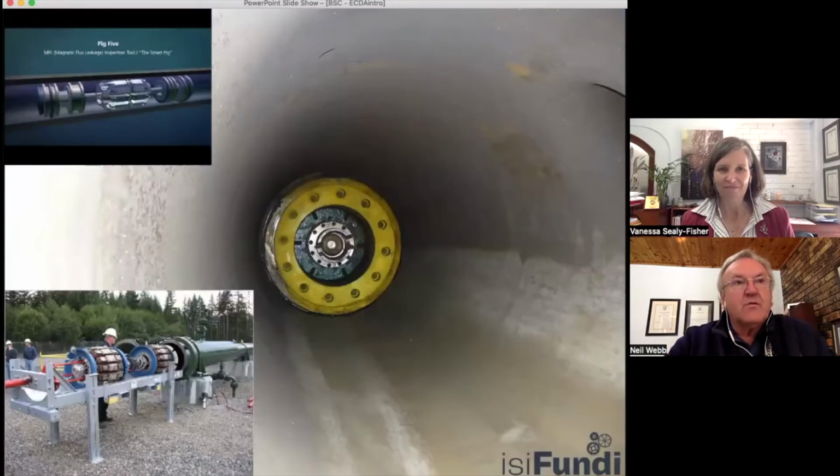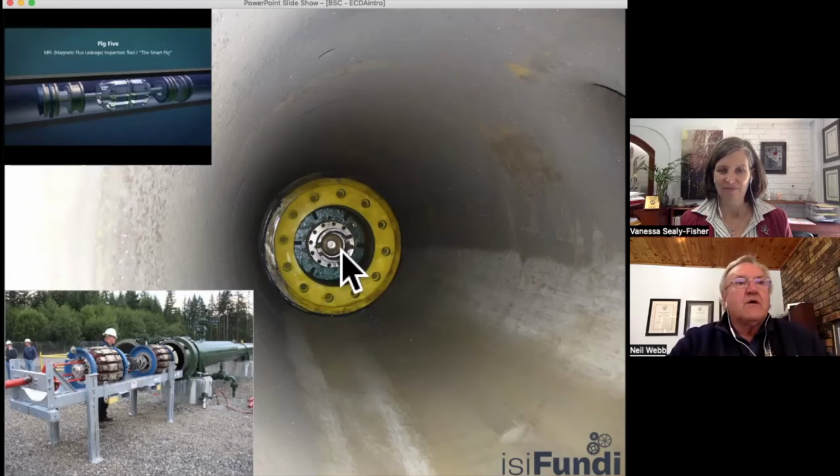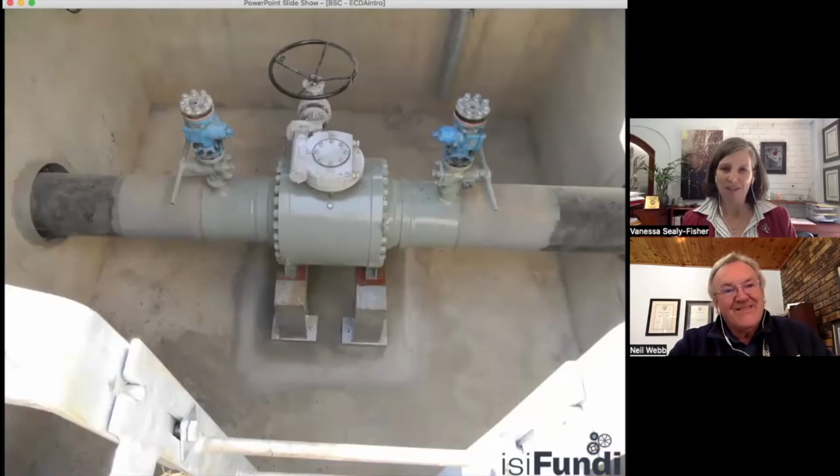Well, certainly we don't want to wait for it to leak to find where it's about to corrode. And in the oil and gas industry and hazardous pipelines, they use a technique known as pigging. A pig is a pipeline inspection gauge. That's where the name comes from. Typically, it is something that you can push through a pipeline, and it's fitted with sensors, as you can see in this photograph over here. And these can tell what the residual wall thickness is, and it can tell you whether you've got internal corrosion or external corrosion, how much, where, how bad it is, and so on. And that's a picture taken down a pipe of a pig on its way. Obviously, your pipe has to be able to carry this.